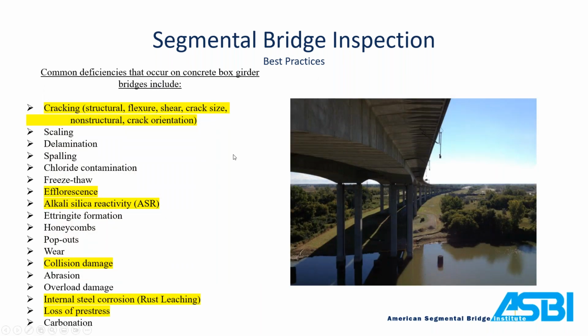So some other common deficiencies to watch out for in segmental bridges. Cracking, I talked about that, and I'll get into the different types of cracking and kind of how to identify those. Some of these other highlighted ones, efflorescence, that's a result of moisture and chloride penetration affecting your concrete. Usually you're going to see some rust leaching in conjunction with efflorescence. Alkali silica reactivity, ASR, a lot of times you have cracking or delamming you really can't explain. It typically has something to do with the aggregate or something with the concrete mix.